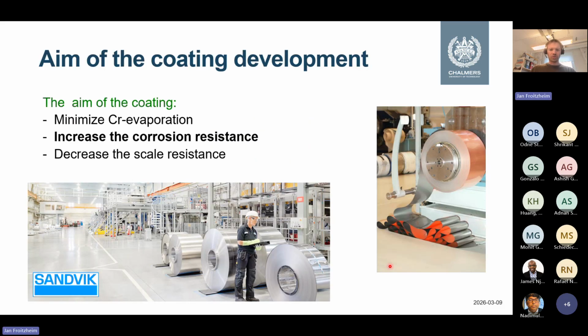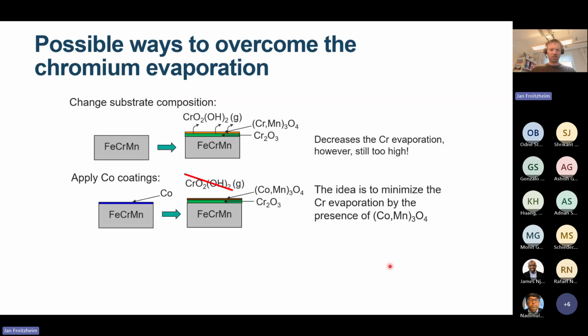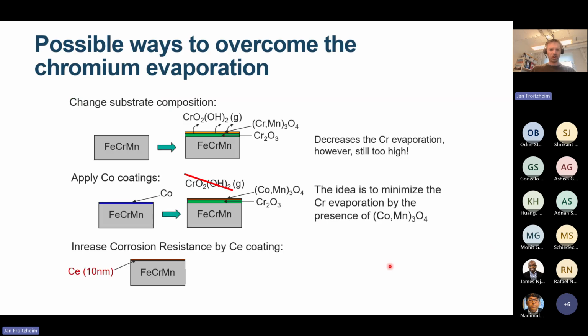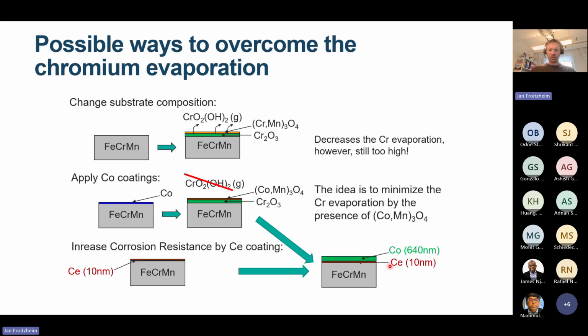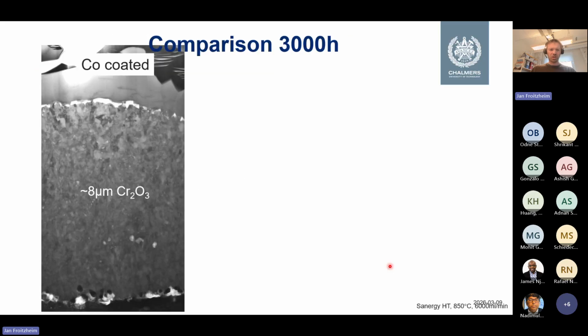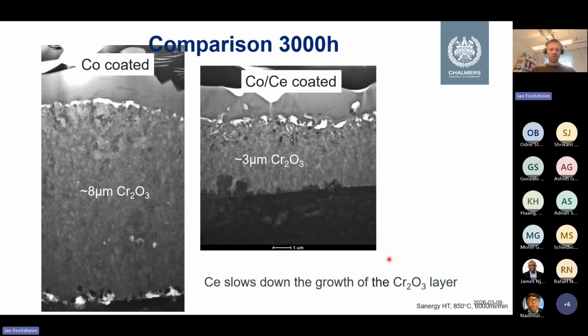Then we wanted to increase the corrosion resistance. To do that, we combined this cobalt coating with 10 nanometers of cerium underneath the cobalt. Again, here's the TEM image of the oxide scale, and here is with adding 10 nanometers of cerium, same magnification, same exposure conditions. You see that this chromia scale is roughly one third of what we had with only cobalt. So the cerium slows down the chromia growth quite significantly.